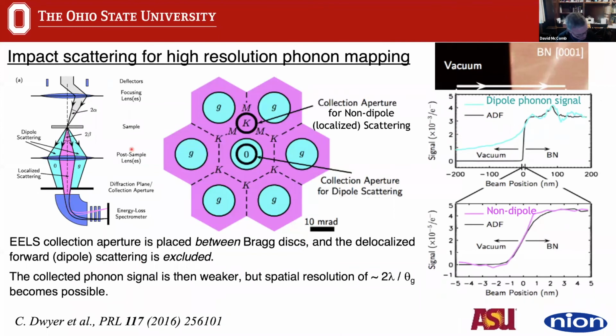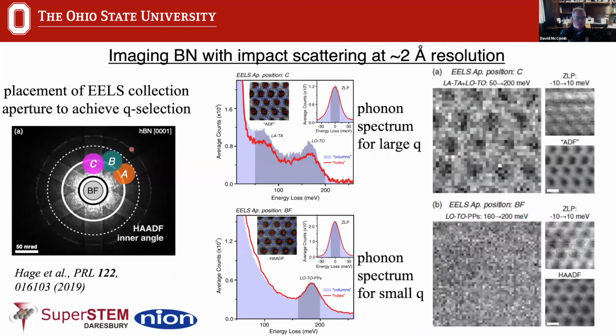And then just to finish this off, I said that we could really only do this with low spatial resolution, but the recent work, first of all, theoretical work by Christian Dwyer at Arizona State, and then more recently, the experimental work from Frederick Hage and co-workers at SuperSTEM in the UK have shown that in fact, by using impact rather than dipole scattering, looking in this low energy part of the spectrum, you can actually get phonon spectroscopy with relatively high spatial resolution.